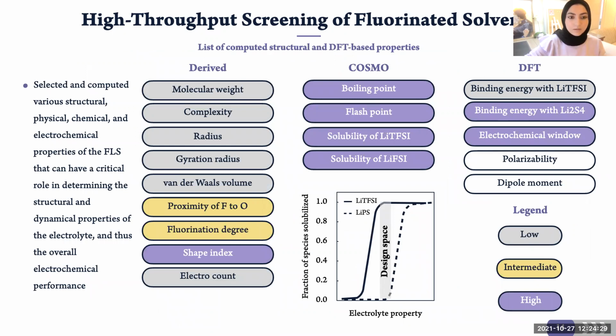This slide shows all the properties that we included in the screening, and all of them have a critical role in determining the overall performance of the lithium-sulfur electrolyte. And they can be categorized into 3 different groups. Derived properties, which are based on the structural features or composition of the solvents. For example, the molecular weight, radius, and van der Waals volume can affect the viscosity of the entire electrolyte and are desired to be in the lower range. Complexity, for example, is desired to be low as well for the higher synthetic accessibility to that solvent.